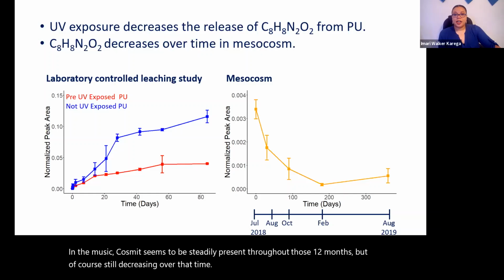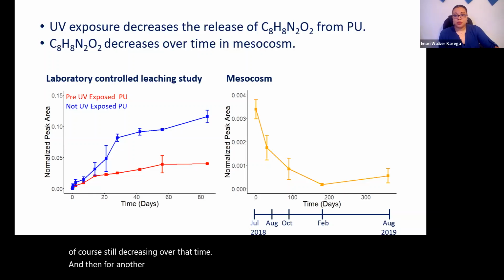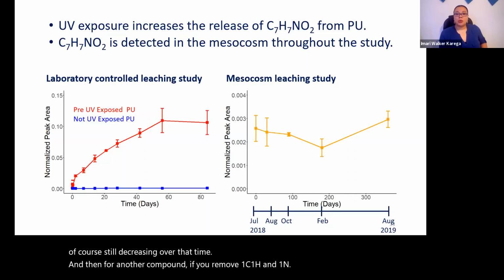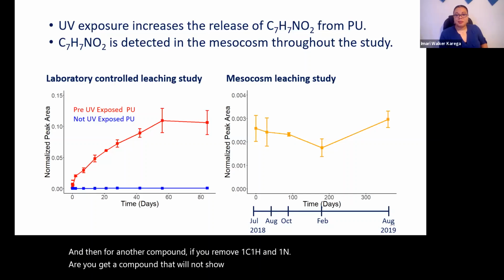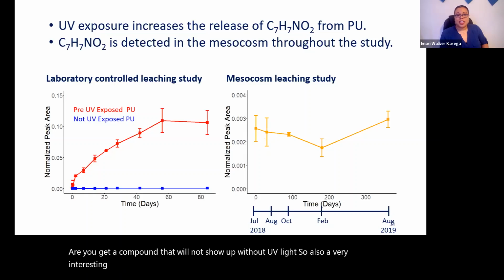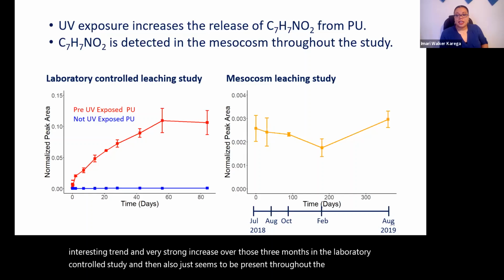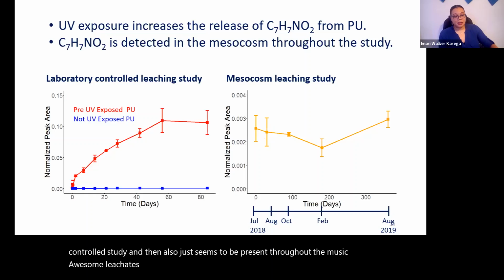For another compound, if you remove one C, one H, and one N, you get a compound that will not show up without UV light - a very interesting trend with a strong increase over those 3 months in the laboratory controlled study. It also seems to be present throughout the mesocosm leachates for those 12 months and might show a slight increase toward the end of the year.